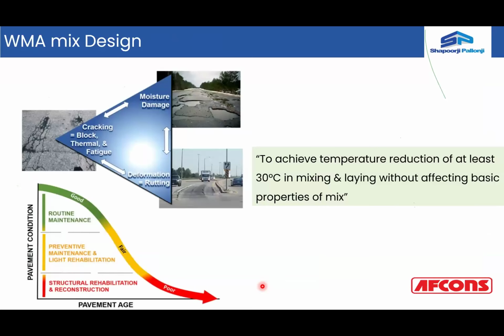Now, in totality, the warm mix asphalt helps you to address 3 things. One is the moisture damage of the aggregates. If the aggregates are susceptible to moisture damage, then it will lead to raveling and then scaling. And then, of course, this further develops into block cracking, thermal cracking, and fatigue. And also, it addresses a lot about the deformation, the rutting formations also.